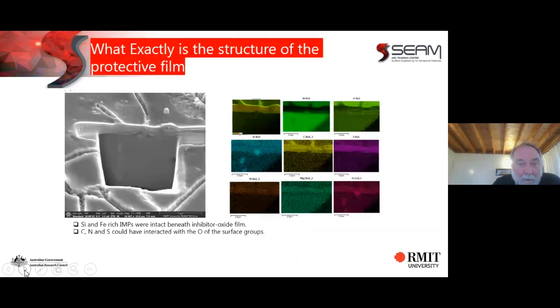Lastly, this is a FIB-SEM looking right down at this edge here, looking at how an inhibitor layer builds up. This square, I hope you can see where my arrow is, is the metal surface. Right above it is the inhibitor layer, and above that is a protective layer placed on the FIB in order to look at it. And here's some EDS of the layer. This is just a quick way to show we're not exactly sure what these protective films are. They tend to be 10 nanometers or larger, so they're not just a simple monolayer of inhibitor. They're a complex layer that we need to explore more.